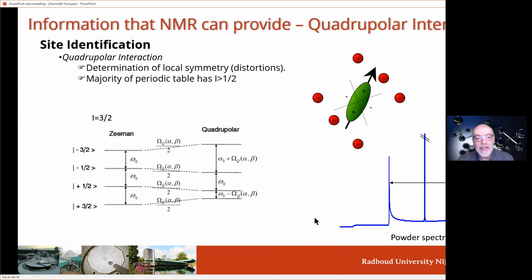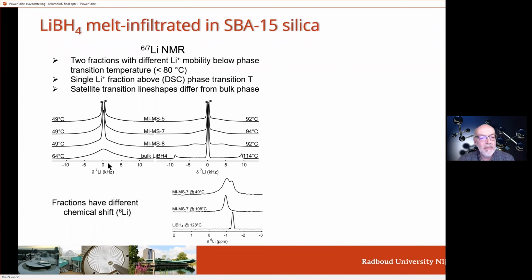So now when we revisit this lithium spectrum for the bulk, we know that the lithium actually is rather rigid. And in the high temperature phase, it moves about. And that gives us this nice, textbook example of the line shape, as I just showed you. But for these melt-infiltrated samples, we get all these line shapes in between.